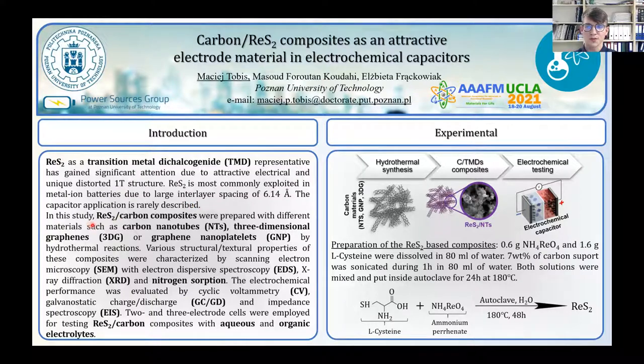In these studies we have prepared various ReS2 carbon composites, for example carbon nanotubes, three-dimensional graphene, or graphene nanoplatelets by hydrothermal reaction, and used them as electrodes in electrochemical capacitors.